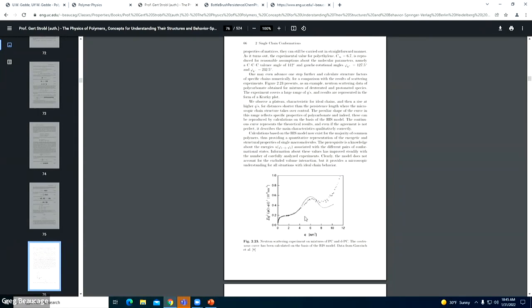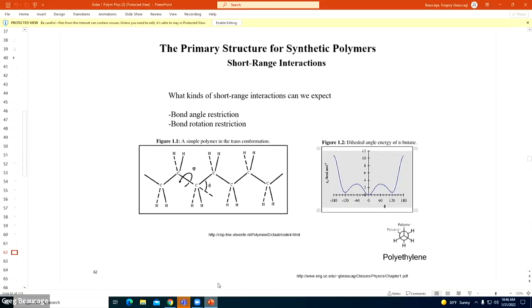This is a demonstration. This is a diffraction pattern. A Q of 1 is something like 5 to 10 degrees, so Q at 10 is like 100 degrees 2 theta in a diffraction pattern. This is the amorphous halo of polycarbonate. The prediction is the line and the measurements are the dots from the Flory rotational isomeric state model. So it works pretty well. So anyway, that's the potential thing.